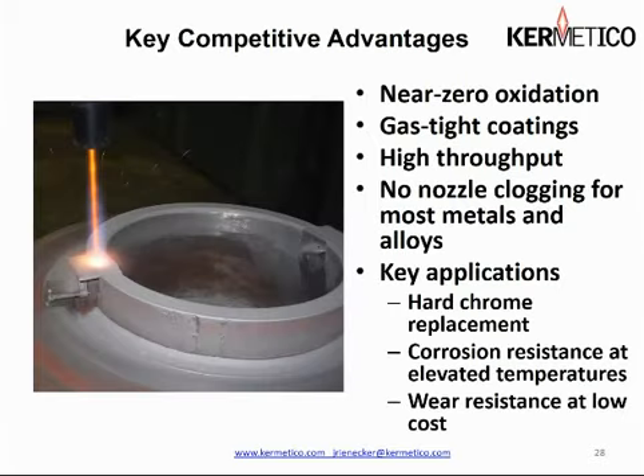Some of the advantages that arise from using the HVAF process or our reduced oxygen HVOF process are that we have almost no oxidation of the feedstock material. Coatings we produce, almost everything we spray is gas tight. We have high throughput, as I said, carbide's up to 60 pounds an hour, actually a little higher than that. Metal's up to 50, and deposit rates, deposit per pass, between 1 and 2 thousandths per pass, and that's even for carbide.